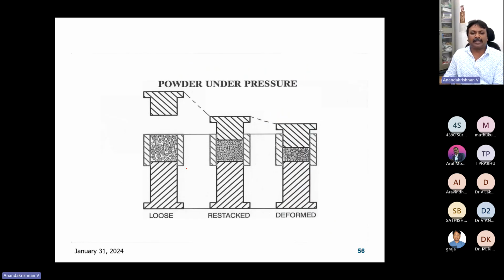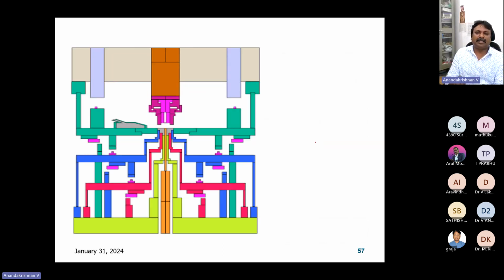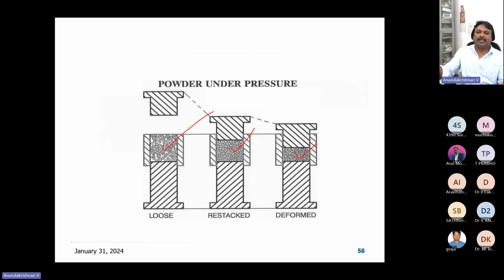So what happens when you are compressing the powder inside a closed container? Initially, there will be a lot of loose powders, a lot of cavities, pores, you can see, and then you can see it getting restacked, and finally it will get deformed. Now the additive manufacturing setup usually involves not only powder spreading. Some of the technologies now under research are that you can roll these powders to create a uniform thick layer.